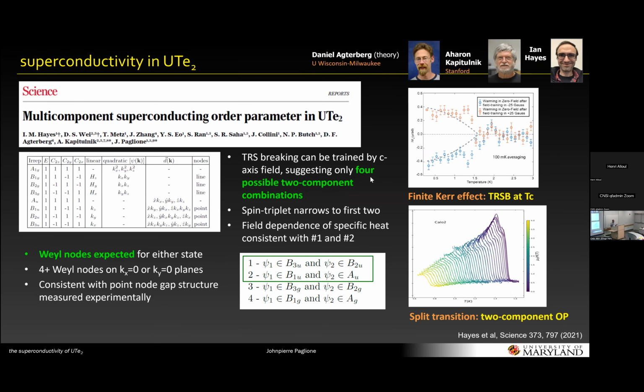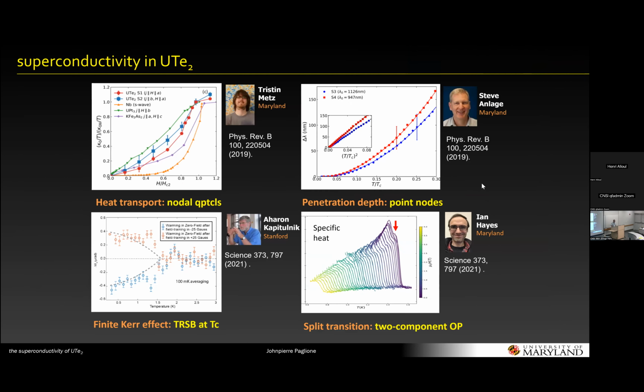That was consistent with our original interpretation of our data of heat capacity, and then collaboration with Aaron Kapitulnik, seeing a magneto-optical Kerr effect onset at TC, in that there's a splitting of TC in the heat capacity data, and there's a Kerr onset, which would be consistent with a multi-component order parameter. So meaning that there's a complex component. So that's since come under scrutiny.